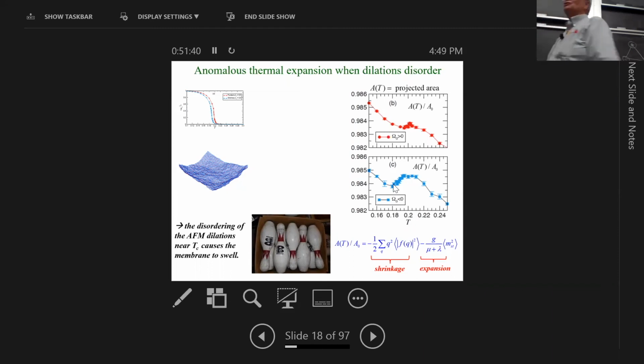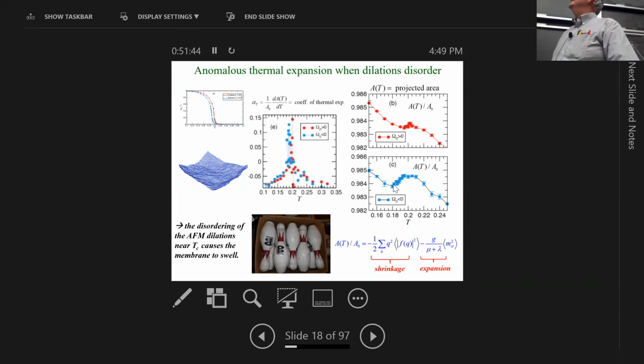In fact, it causes the slope, it turns out, to diverge. So you get a diverging thermal expansion coefficient. In fact, it's a specific heat-like divergence at the transition. It's a pretty strong one. It's stronger than logarithmic anyway. So instead of having a negative coefficient, you can control the coefficient of thermal expansion just a little bit like, if you go above the freezing point of water, there's a place where the thermal expansion coefficient vanishes. Okay, well, here it goes to infinity.